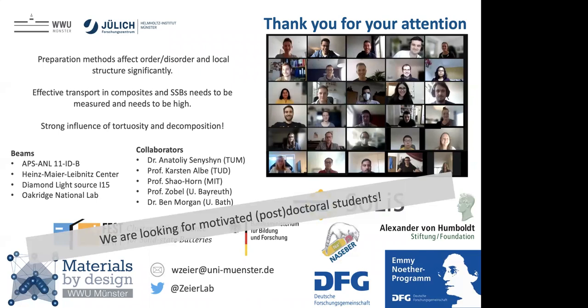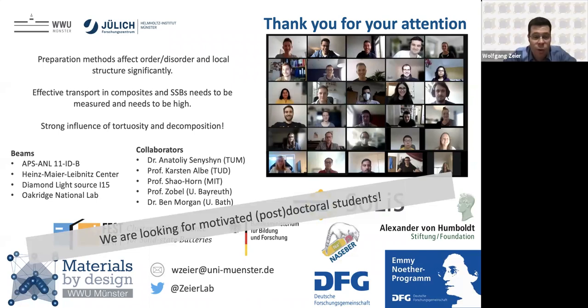And are these materials by any chance entropy stabilized? I would assume so. At least the ones that we quench from high temperatures like that. But is this order purely entropy based? Well, we don't know. We try to calculate how much disorder we would get from entropy, and the disorder increases if we use configurational entropy, but it doesn't truly match the experimental data.